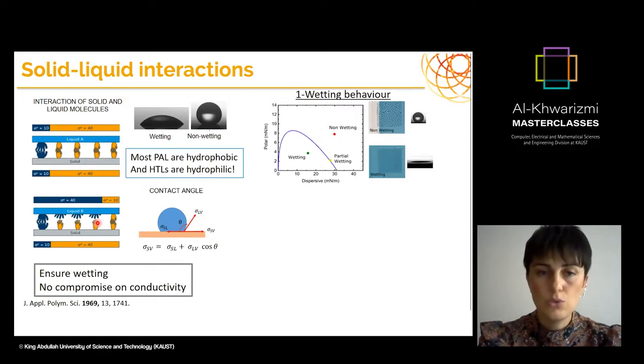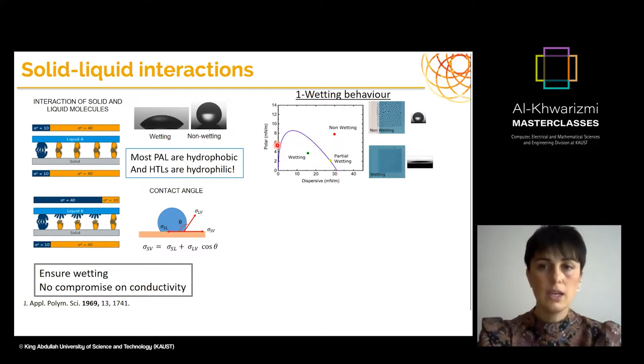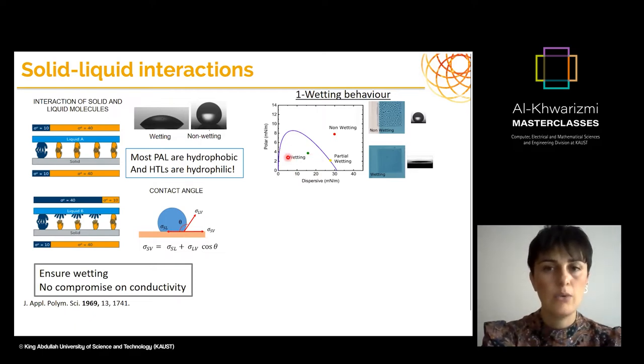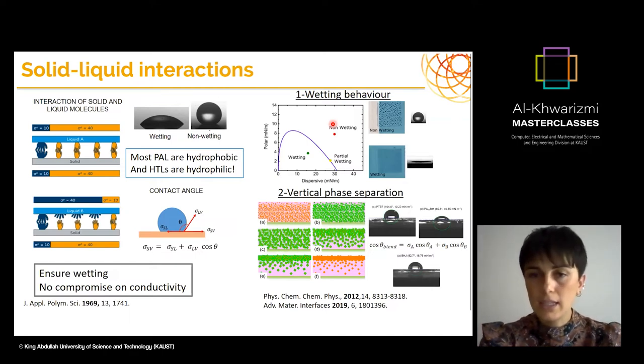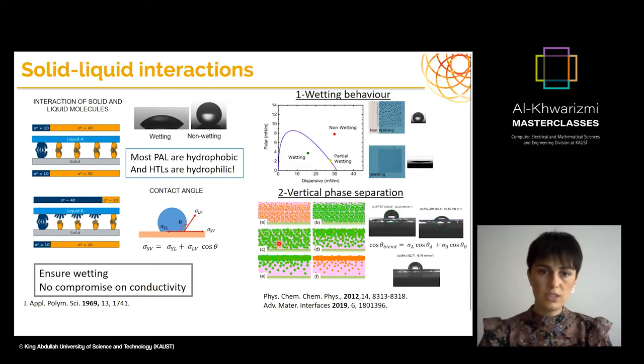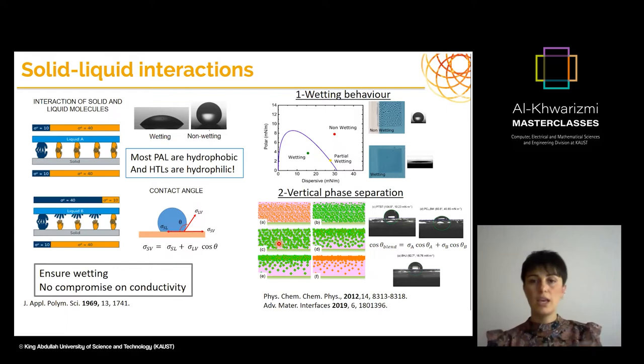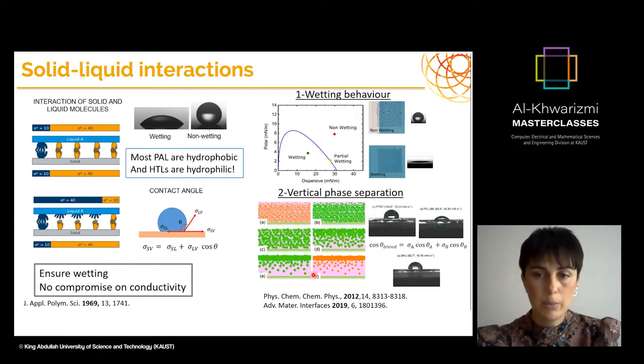What we can do is use contact angle measurements along with measuring the polar and dispersive forces, and you can obtain a so-called wetting envelope of your ink, in this case the PTB7-Th and 4F blend I told you. As if it was your solubility sphere, think of it in 2D: anything lying in this wetting envelope will wet your surface, and anything outside will have a non-wetting behavior. And further, by measuring the contact angle, you can also understand the vertical phase separation within your layer. Basically, if your surface energy is changing because of the different materials used, for instance polymers and small molecules, and polymers tend to go up because of their surface energies, you can control this vertical phase separation or understand if it works or not.